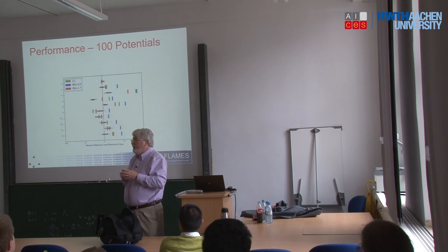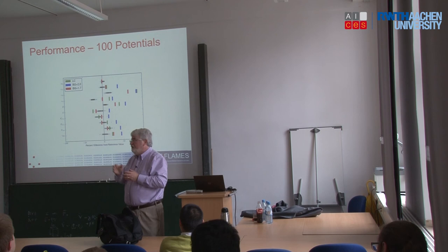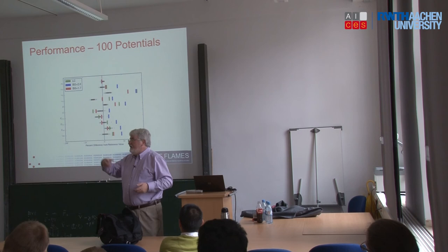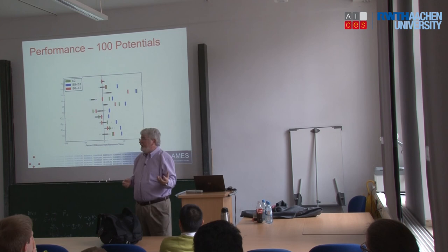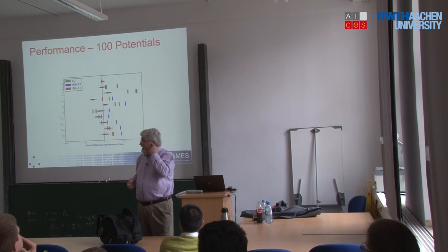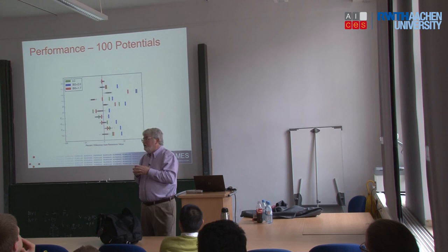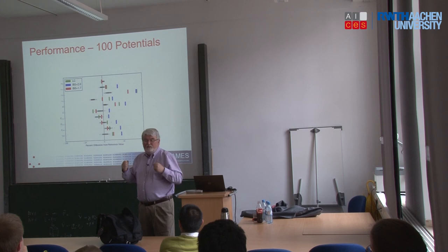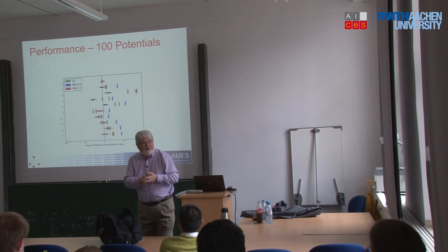But then we can also do things like principal component analysis. You might find out that this parameter in front of your sine function is linearly correlated with another term, which basically says that term isn't doing you any good, because it's not capturing something which isn't already captured somewhere else in your potential. That would say you're probably adding complexity without adding additional physics. You could then start doing analyses of this. For example, you could take a Tersoff potential and the Stillinger-Weber potential, put them head to head for silicon, and work out all the distributions and all the compromises,